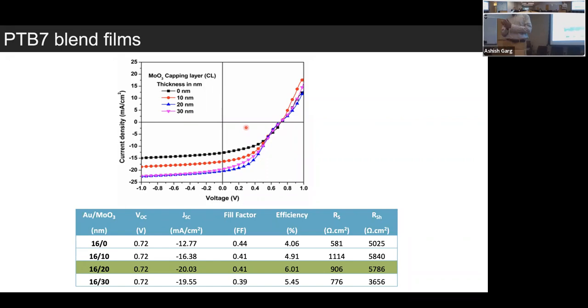So essentially what it says is that by making this dielectric stack, you are coupling about 70 to 80% of light, which is a lot of improvement as compared to a plain gold electrode, which gives you 40% transmission. So by making this multi-layer electrode, you can improve the transmission of the stack by roughly 2 times and increase the light coupling or light absorption in the active layer. By no means is it a perfect device as yet, because making it on steel has challenges, but we have been able to ramp up this efficiency for PTB7 to 6%, which is probably the highest obtained on this substrate so far.